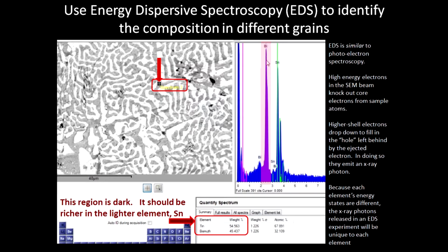But we can see this peak right here that I'm highlighting. That corresponds to an X-ray photon that was emitted by an electron in a bismuth atom falling from a higher shell down to an inner core shell, and that electron was emitted. And so, similar to photoelectron spectroscopy, the height of the peak is proportional to how many of those X-ray photons were emitted. The more bismuth atoms there are, we might see more X-ray photons of bismuth at this particular wavelength.